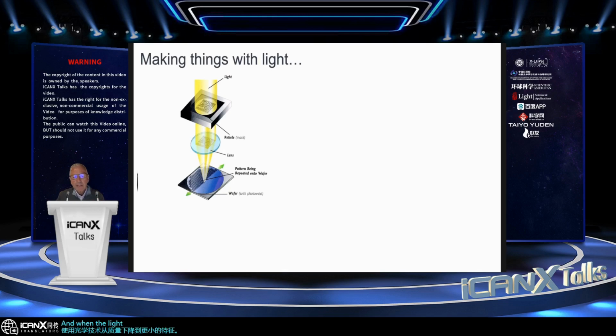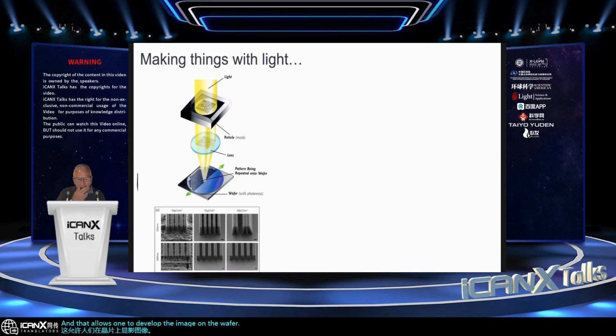And when the light hits the polymer film on the wafer, it induces a chemical change. And a chemical change often is related to a solubility change. And that allows one to develop the image on the wafer. And that image then can be developed and a pattern can emerge. I used words that made it sound like it was a two-dimensional image, an XY image, and for the most part it is. But if you look carefully, there's actually a third dimension. So maybe we'll call it 2.5 instead of three-dimensional.